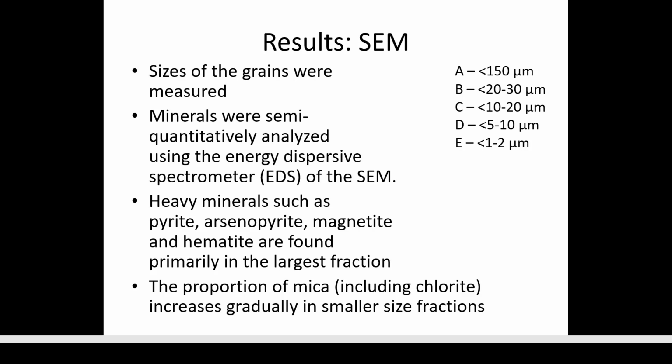Our SEM. First of all, the main reason to use the SEM was to be able to understand the different size fractions. We did all of our analysis based on centrifuging, based on the assumption that the size fractions were perfectly circular and applied strictly to the laws of physics. Therefore, this was the idealized circumstance. Knowing that these different minerals are not perfectly circular, we must look at them under the microscope to be able to determine the exact size fractions.